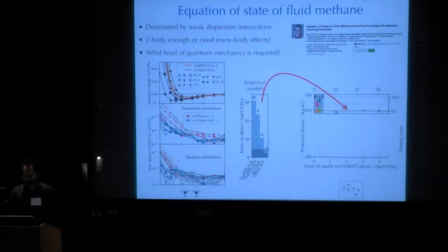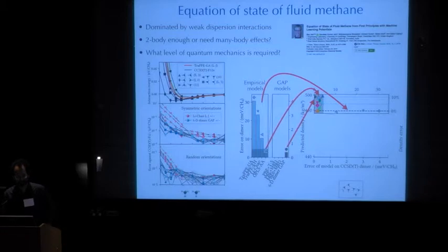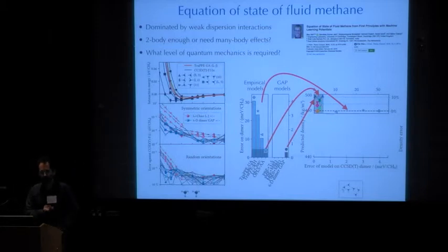What happens if we say, actually, let's get the right answer for the right reason? If I fit the pair of methane energies really, really accurately, I should be getting the density really, really accurately. But that doesn't happen. So this model, the one that's best on the dimer, actually is pretty poor. And we can make an even better model. So this is the zoomed in scale, and this is half a milli-eV, so 10 to the minus 4 on this scale, invisible on this scale, and it's terrible. It makes a 50% error, 20% error on the density.